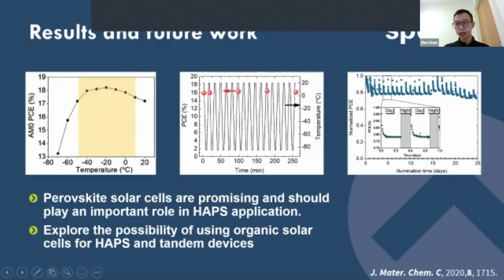And finally, we did some day and night operational testing. So although there is some degradation during the day, it seems that the performance can recover in the night, and then it drops again in another day. So you can see a lot of decay here, but even after 15 times, it can reach back to the original efficiency. So the stability should be fine for this kind of application.